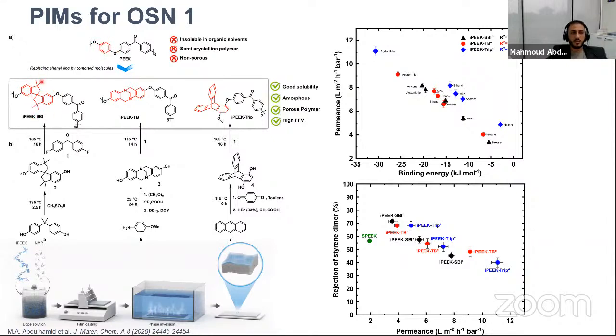Having a kinked unit will generate a porous polymer. So we have selected three different kinked units, as you can see here, and we have tested these units. We have prepared membranes out of them. Preparing membranes for OSN is very simple. You dissolve your polymer to form a dope solution, then you cast it, and then you phase invert it in water, and you end up with a film or membrane for organic solvent nanofiltration.